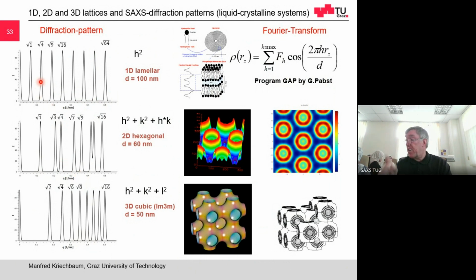So from the position of the peaks, you get the lattice type, and from the intensity of these peaks, you can get the electron density. This is an electron density picture of the hexagonal phase. So you see in the interior, you have high electron density. There, the water is located, and outside you have these hydrocarbon chains, which have a low electron density. So if you insert some tracer, you would increase the electron density in the core, and you would immediately see it if you compare it with the electron density without any tracer. So you can locate your tracer in your nanostructure.